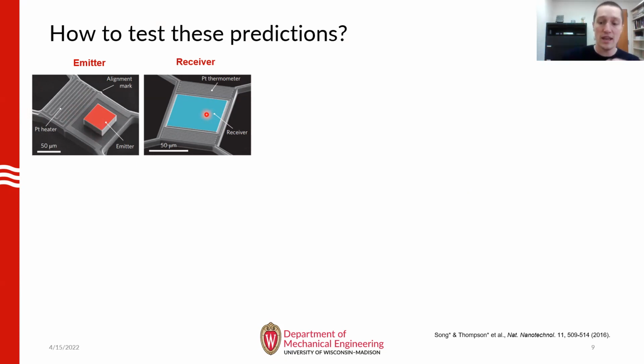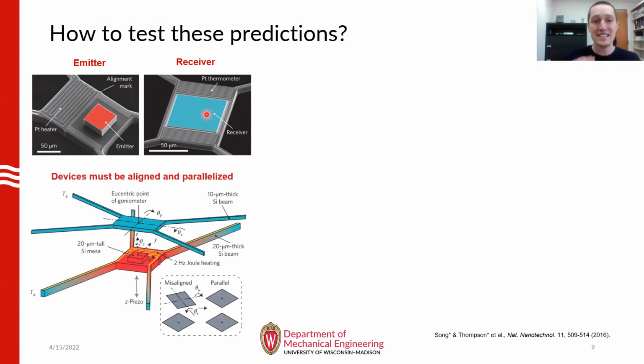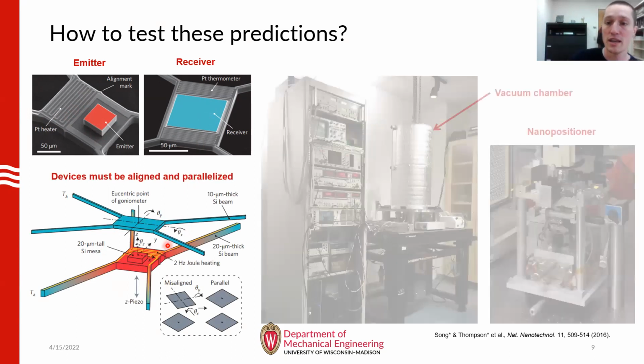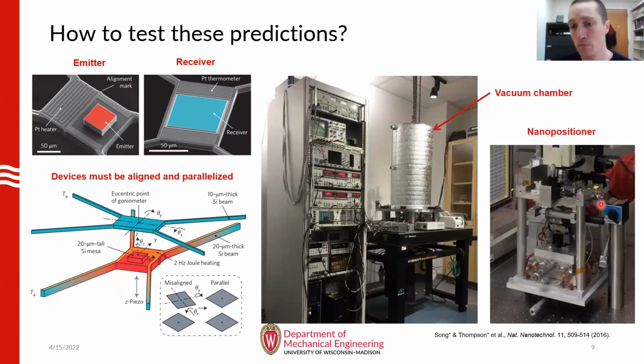So once fabricated, we were able to precisely align and parallelize these two devices in the configuration that you see illustrated below. And we were able to do this using a custom-built nanopositioner, which is shown in the picture on the right. Once aligned, we could then move these devices into a high vacuum chamber here, which is inside of this radiation shield. So under high vacuum conditions, we can essentially eliminate convection from the measurement. So the only heat transfer between these devices is due to radiation.